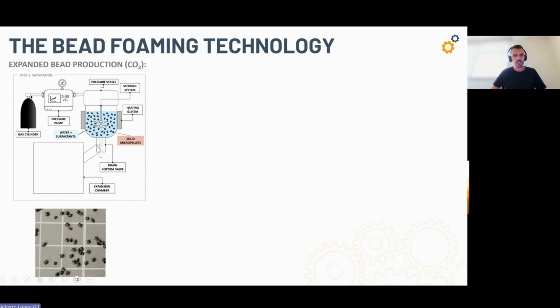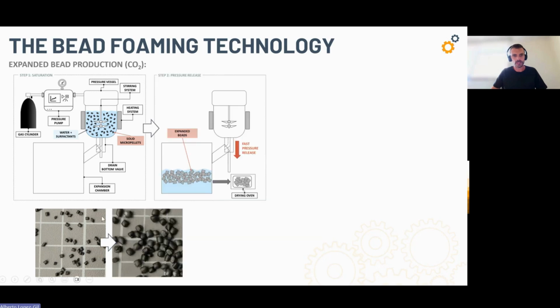This is a technology in which, instead of foaming solid sheets, large in size, with a prismatic shape, for instance, we are foaming tiny micropellets. Micropellets lower than 1 millimeter in size. This is the initial polymer. This is the vessel, which in this case is a stirred vessel. So the micropellets are suspended into water, and then the blowing agent is injected, carbon dioxide, and the gas is diffusing into the micropellets. And when the micropellets are fully saturated with gas, then we open a valve, and the micropellets expand into expanded beads, as you can see here, also very small in size.